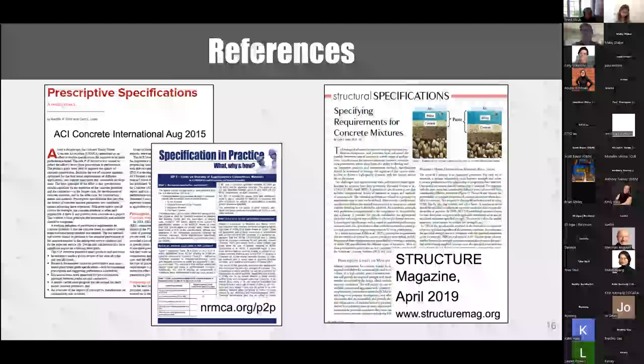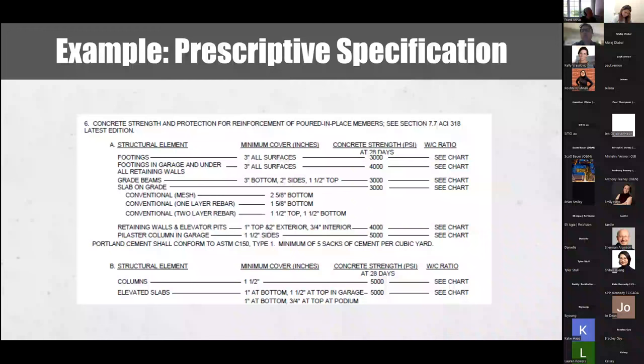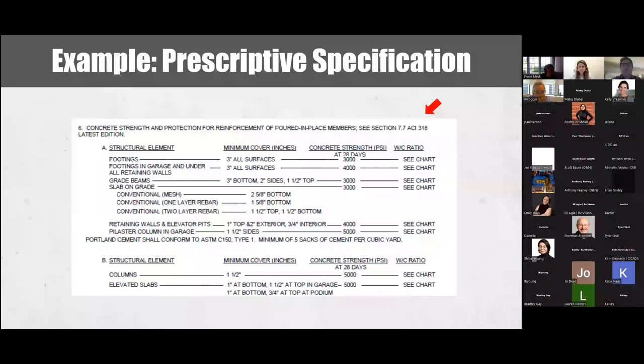So here is an example of a prescriptive specification. Let's review some issues with this. This specification establishes requirements for water to cement ratio for all portions of the structure, regardless of whether there is a durability issue to be addressed or not. We will also see that there's no relationship between the strength specified and the water to cement ratio. The specification requires 470 pounds of Portland cement regardless. Unsure what the intent is here.